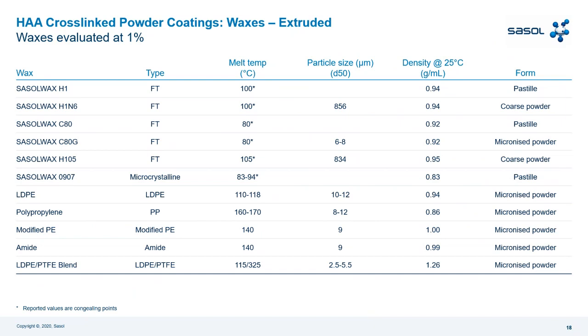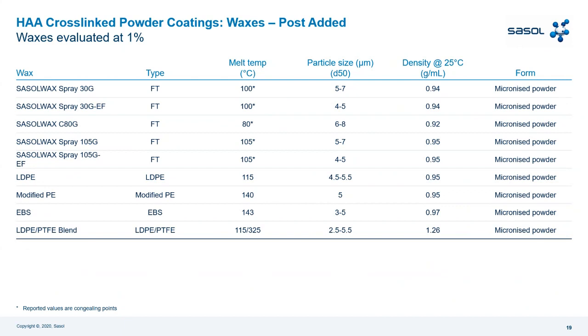Again, we use LDPE, the PP wax, the polypropylene wax, the modified PE wax, that is HDPE, the amide wax, and the blend PE wax and PTFE blend. This is in pre-extrusion. In post-extrusion, we use similar to before, only micronized powder. So Sasol Wax Spray 30G, 30GEF, C80G, Spray 105G, Spray 105GEF. Then we use PE wax, HDPE wax, EBS wax, and the blend PE plus PTFE.